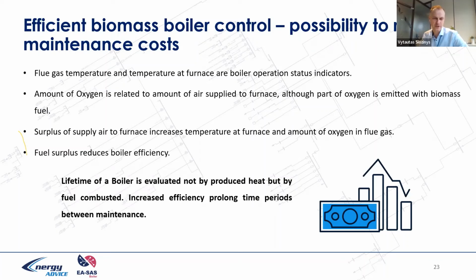Coming back to what we mentioned before, flue gas temperature and temperature at the furnace are boiler operation status indicators. If you have fluctuating temperature and fluctuating recirculation, we have unstable fuel supply. If we have to regulate grate rates quite often, that means fuel water content changes, the flue gas recirculation and drying process are not stable, and automation is not capable of stabilizing this. So surplus air supply to the furnace, increased temperature at the furnace, amount of oxygen in the flue gas, and fuel surplus reduce boiler efficiency. And finally, the lifetime of a boiler is evaluated not by produced heat but by fuel combusted. Increased efficiency prolong time periods between maintenance.